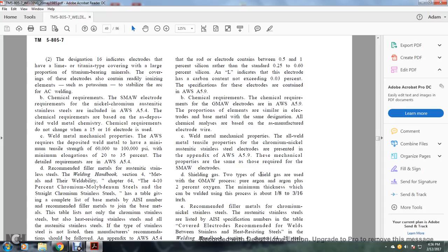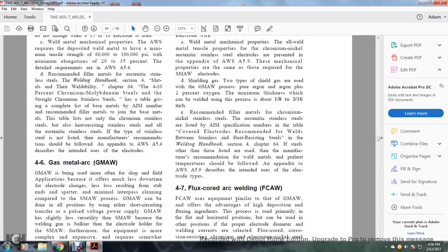Shielding gas. Two types of shielding gases are used for gas metal arc welding: pure argon and argon plus 2% oxygen, which can be used for processing minimum thicknesses of 1/8 to 3/16 of an inch. Recommended filler metals for chromium, nickel, austenitic stainless steel